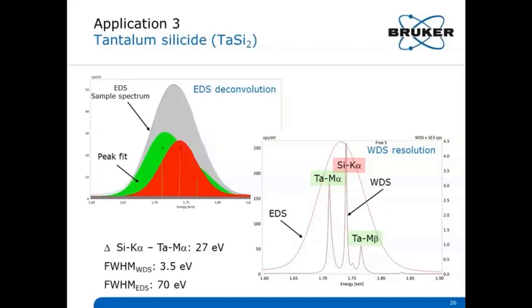So here we see the result for EDS peak deconvolution as well as for WDS peak resolution on the lower right. The energy range scan is shown in the graph on the lower right, and there you can see that WDS nicely resolves the single peaks of silicon and tantalum.